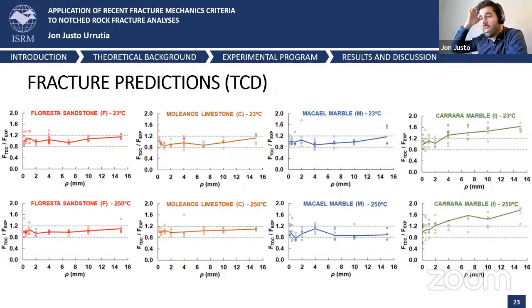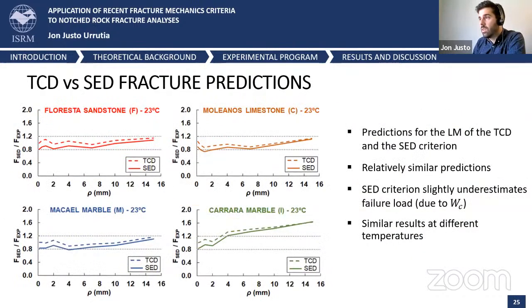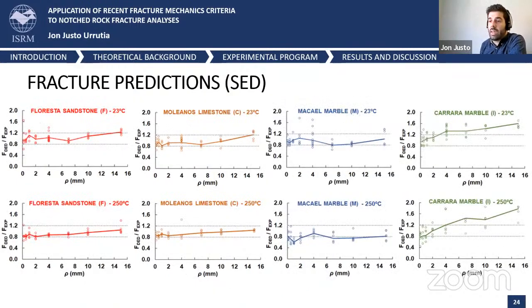While the first row corresponds to the results performed at 23 Celsius degrees, the second row represents those results at 250 Celsius degrees. We can consider relatively reasonable fracture predictions in general within a strip of plus minus 20% in all the cases. The Carrara marble, of course, is the exception, as expected from the non-linear behavior, even at room temperature. And these are the same results for the case of the strain energy density criterion. We also obtain relatively accurate predictions in all the cases, except for the Carrara marble.